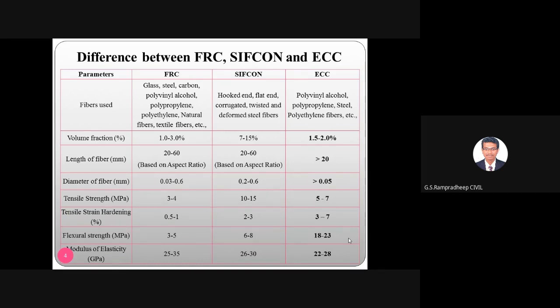Flat end fibers, corrugated fibers, right? Twisted and deformed steel fibers, which will have more capacity of arresting the shear, right? And for ECC, the most common fibers are PVA because it induces maximum tensile strength to the composites, then polypropylene, steel, and polyethylene fibers. So these are some of the fibers normally used for ECC research. As far as volume fraction is concerned, for FRC they will go up to 3%, minimum 1% of the fibers. And SIFCON, 7 to 15%.